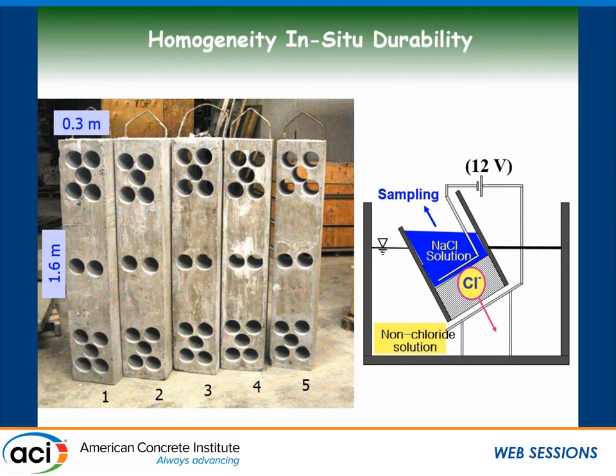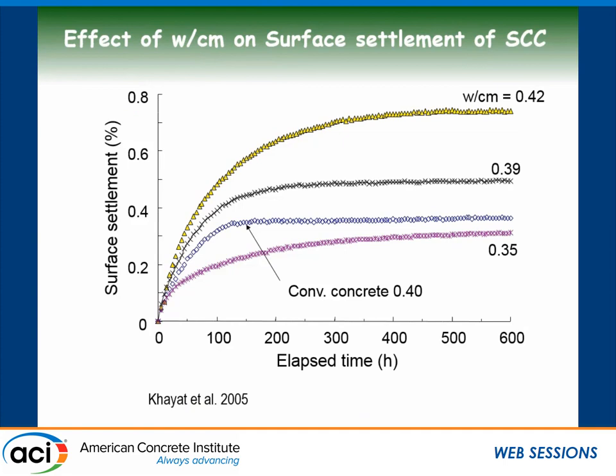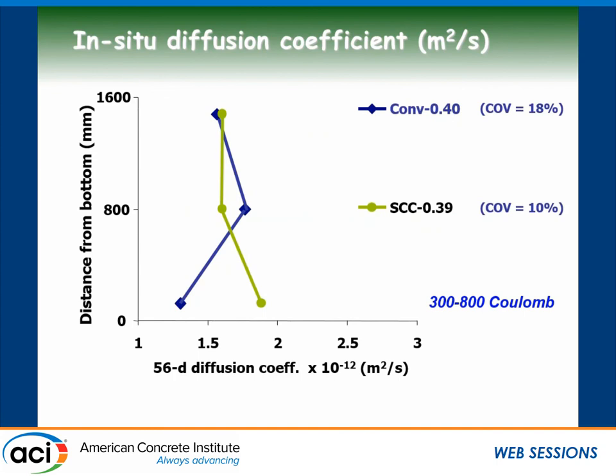And this was done for SCC, and here I'm showing you again something I presented earlier, and that is the effect of the water cement ratio on surface settlement. All of them have the same slump flow, about 27 inches. Surface settlement is decreasing by reducing water cement ratio. And if you look at the distribution of the in-situ properties, so this is a 56-day diffusion coefficient. By the way, all of these concretes have a ternary binder, silica fume, and fly ash. And look at the distribution.